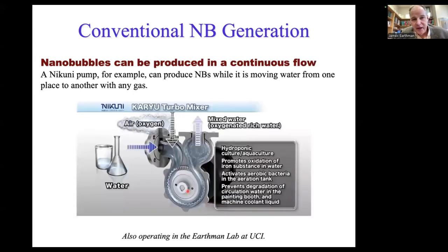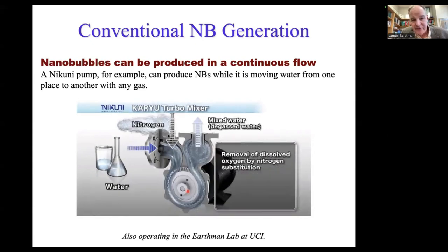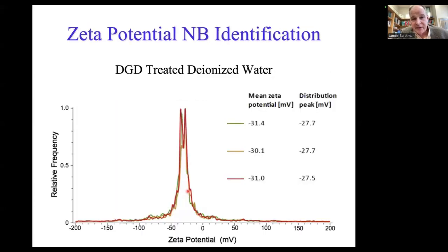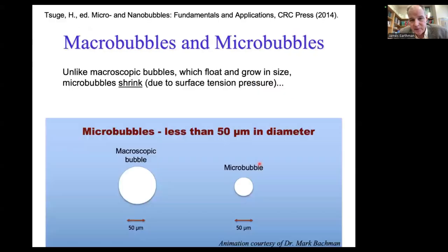Okay. Here's another method for making them. This is called a Nikuni pump. It's made by a company called Nikuni in Japan. They have an American division now that are creating these pumps specifically for generating nanobubbles. And they can show you that you can put different gases in the nanobubbles and create nanobubbles with different gases in them. And so if you take nanobubbles from those types of techniques, this is from the seltzer bottle, this dissolved gas decompression, you do get the zeta potential in this range of minus 30 to minus 40 millivolts, which you'd expect for nanobubbles in deionized water. So the problem is this.